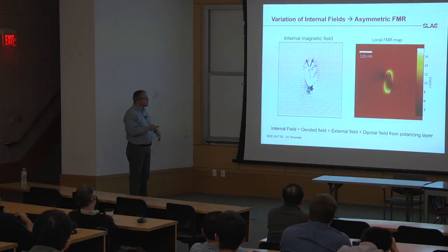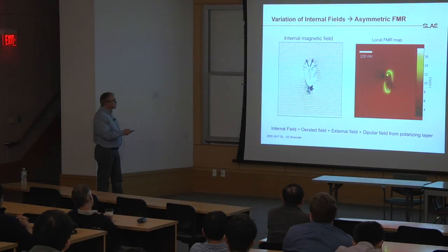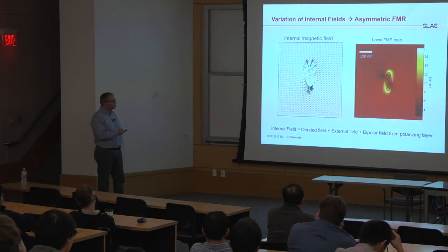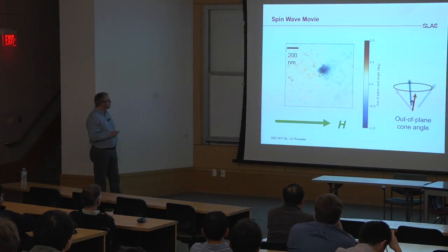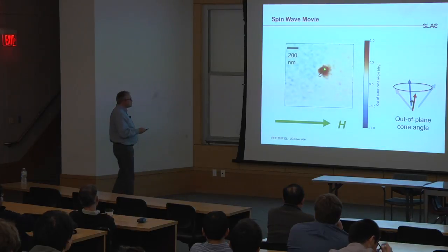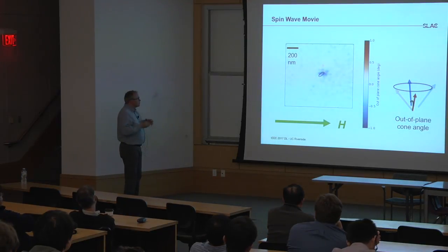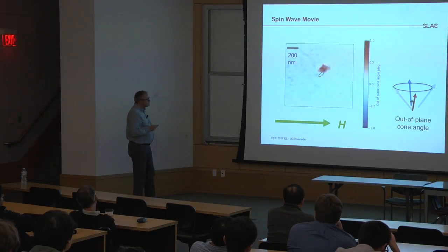So naively, one would expect that it is homogeneous where the nanocontact is, but it isn't. It's very inhomogeneous, and it actually goes much higher than the background on the top and the bottom, and it's lowered on this side, and it's actually lowered preferentially into one direction. And that's exactly what we see, if we go back, that this would be the direction in which the ferromagnetic resonance frequency is lowered. So there's a potential valley where magnetic energy can escape, a spin wave can escape, and that's exactly what we see. That's nice to think about.